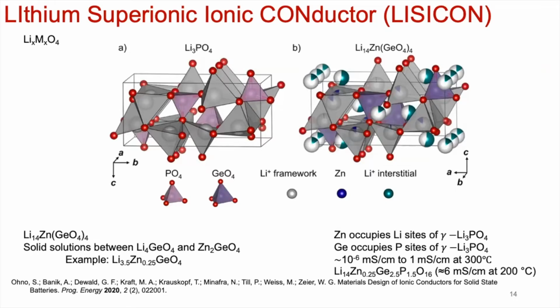And you have to start somewhere, and you're not just going to magically find this compound. So people have studied these type of compounds to understand, well, what is it? How do we engineer high ion conductivity? How do we isolate variables like atomic disorder? Does that help the lithium ions migrate? What about opening that bottleneck that we're talking about, replacing with larger anion, or create aliovalent substitution so that there's chemical disorder? So people play around with this, with a systematic chemical reasoning to then get to this particular composition.